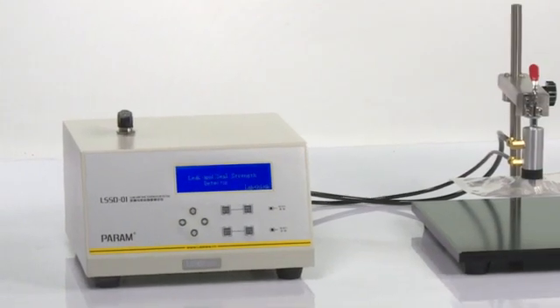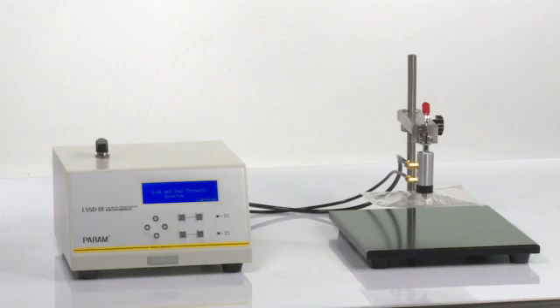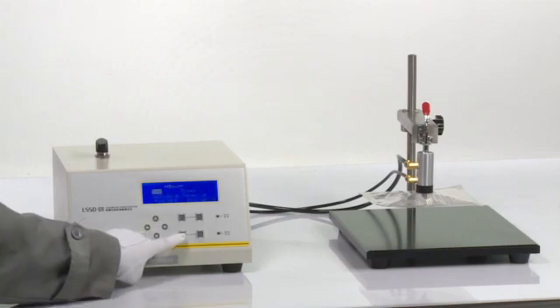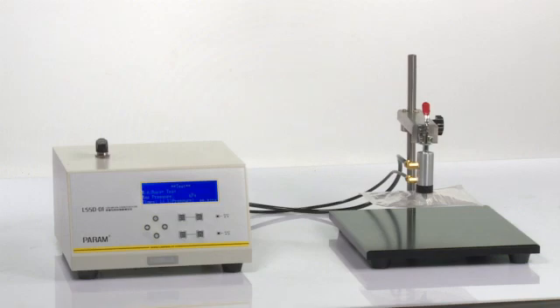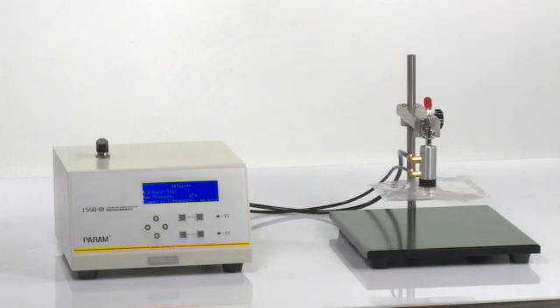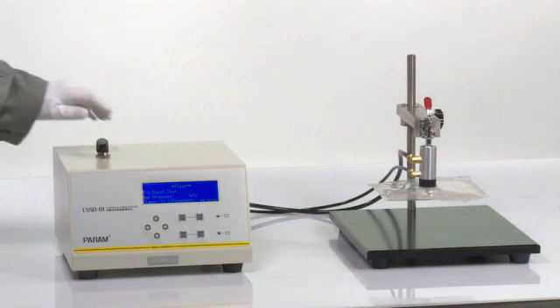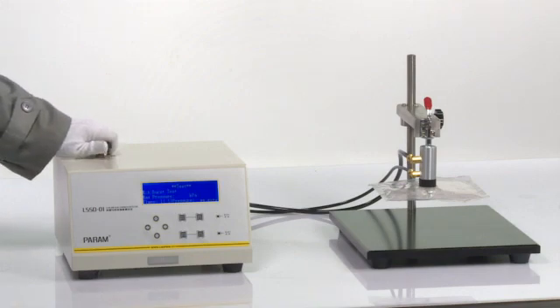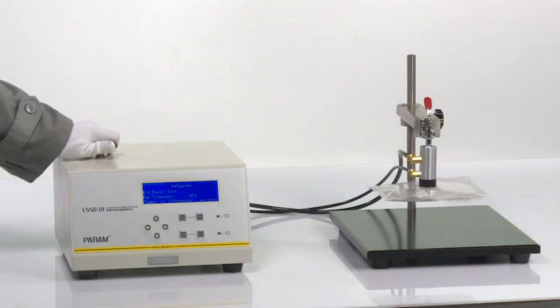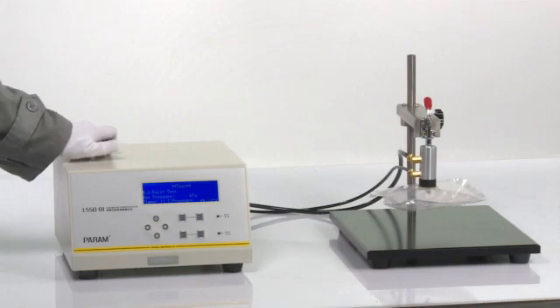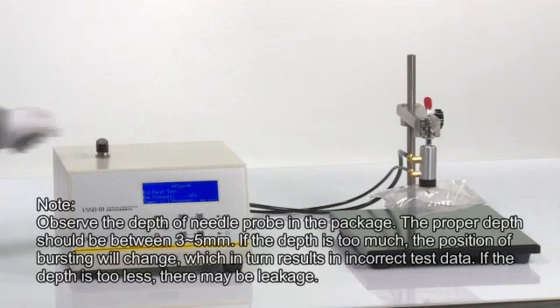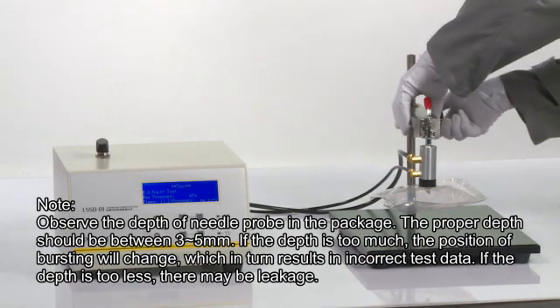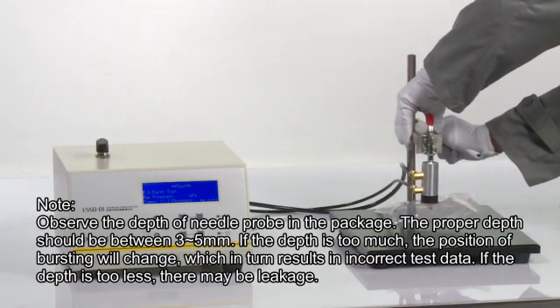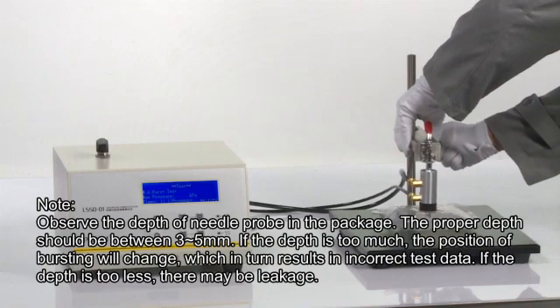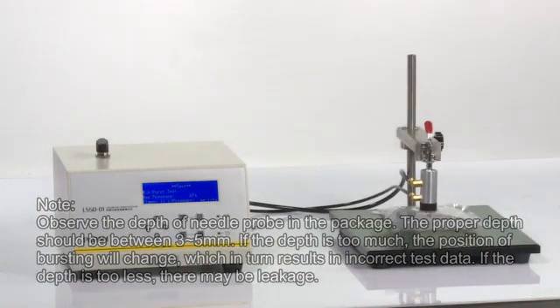Make sure the flow regulator on the instrument is closed. Highlight test item by moving the cursor. Press test button and enter test screen. Rotate the flow regulator 3 to 10 degrees counterclockwise from the shut-off stage until there's gas flow coming out slowly. Fill test gas until the package expands completely. Close the flow regulator. Fasten the holding handle after the needle probe is adjusted to desired position.